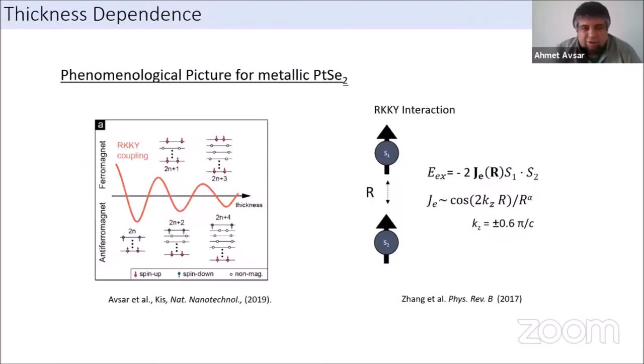And then this also brought us the question: is it the RKKY type of interaction that we should expect? Because based on our theoretical predictions, we do see the magnetism only once these magnetic impurities are on the surface, and then they can only talk to each other through the conduction electrons, and that could be the origin of the magnetism. Okay, and here is how the magnetic exchange coupling depends on the distance between these magnetic impurities.